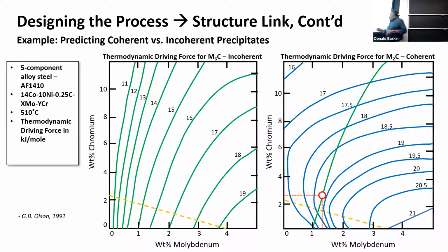Okay, so if you look over here, you think about how you're changing the composition here. At some point, I think it was 15 kilojoules per mole, you start to have corrosion problems because of the material that's forming in here. There's like a galvanic couple, maybe, and read some more on this. Okay, so you know that you can't really go for less than 1% molybdenum and more than about 1.9% molybdenum, somewhere right about there, right? So you're on this line. Then you want to find the highest value of the driving force for the M2C carbides.